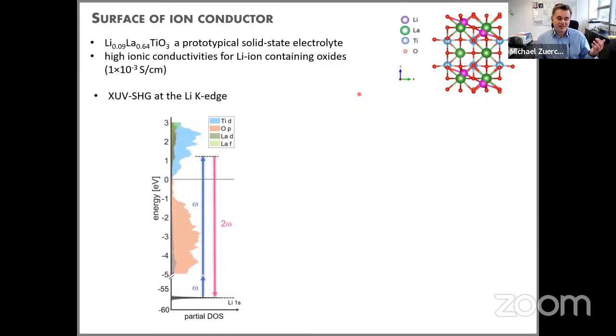What we actually want to study is this electrolyte in contact with an electrode, to study the lithium mobility at the buried interface. As a first step, we set out to measure the surface first, to see what we can see and how we can interpret it. The experiments here were done at SACLA in Japan. We went resonant with the lithium K-edge, with 2 XUV photons of half the energy of the K-edge transition for lithium.